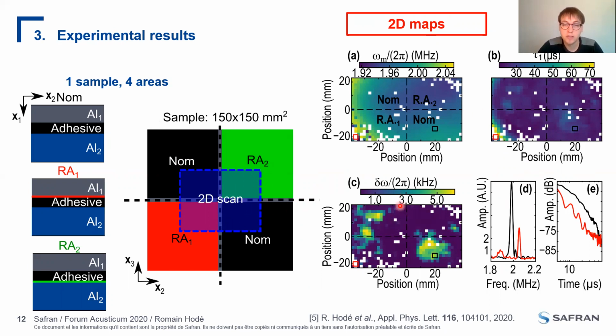And you can see here that for the identification of the parameter delta omega, this parameter is the highest for the 2 nominal areas. And you can also notice that here in red, you have the signal where we have a frequency around 1.9 megahertz, and we have a beating phenomenon now between this frequency and this frequency. This can be observed with the attenuation profile here. So this is due to the beating phenomenon between these 2 frequencies that are really large.